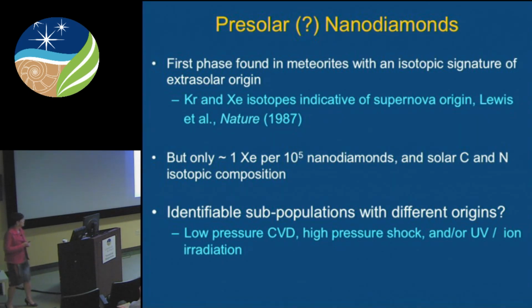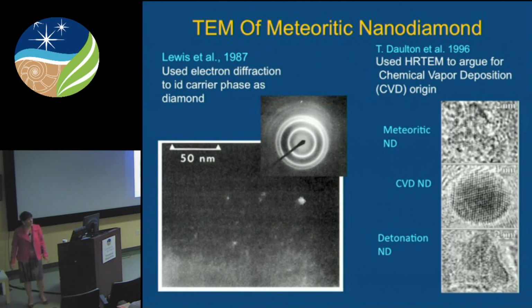And there is no way yet to get the isotope composition of an individual 2 nanometer particle. So there are people trying with the atom probe to get carbon isotope signatures nanodiamond by nanodiamond, and they've had some reasonable success, but it's still fairly dicey, and you certainly could not measure these isotopes in the individual nanodiamonds. So we can look at the nanodiamonds using transmission electron microscopy. In fact, the first discovery paper in '87 used electron diffraction.